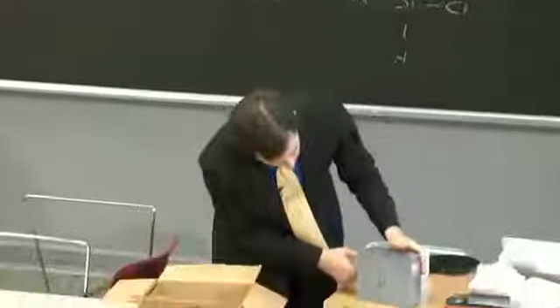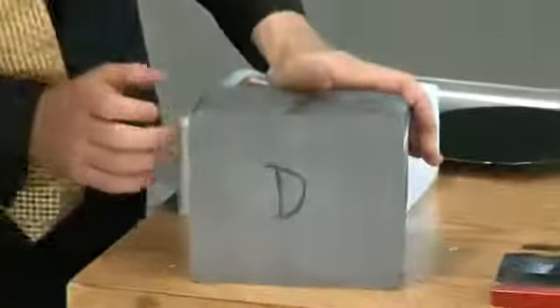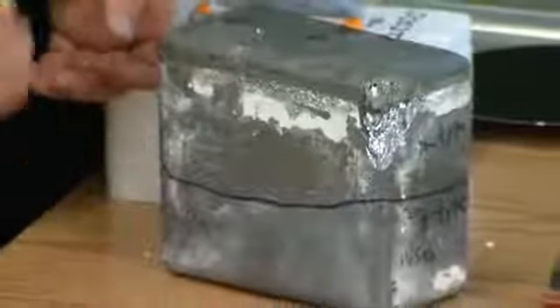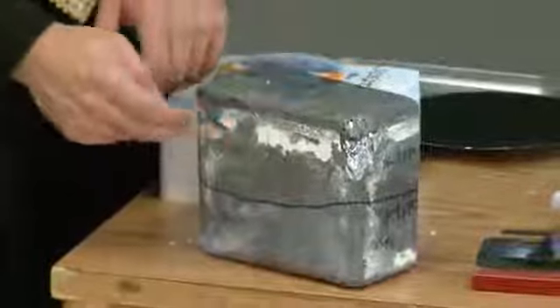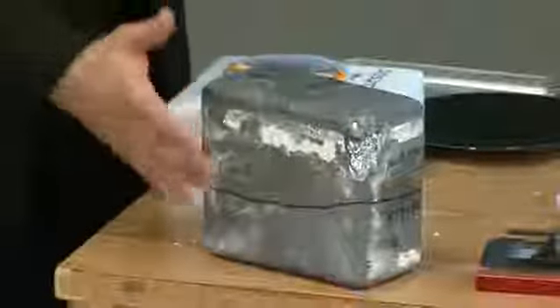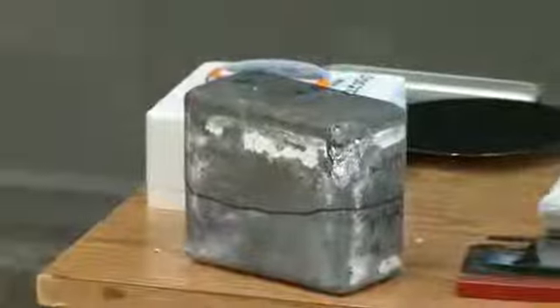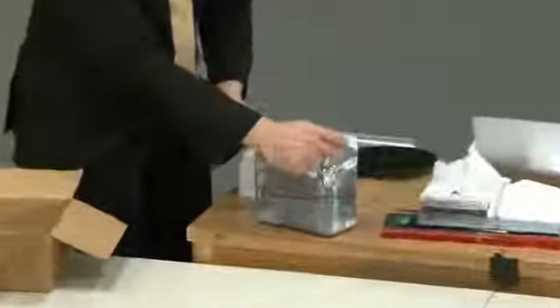And the reason it's cooled from the bottom up is because, and here I guess you'll actually have to come up and see this after class. It's rather difficult to see from here. But this is a cross-section of a small ingot. This is the outside of the ingot where it was contacting the wall. These little pieces of white stuff that are flaking off are the fused quartz silica that forms the crucible wall, and the silicon nitride coating that formed the anti-stick coating that prevented the silicon from sticking to the crucible. And so it's kind of rough and corrugated, but if we were to rotate this around and look at the inside, this here is a cross-section of the actual ingot from the inside.